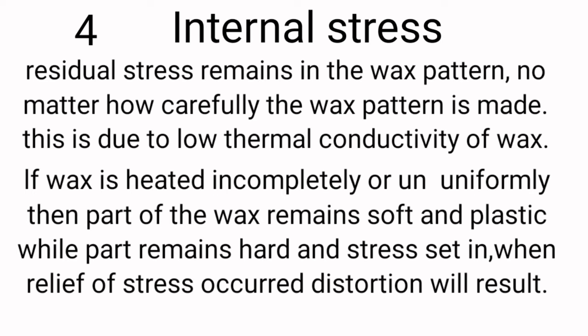Number 4. Internal stress. Residual stress remains in the wax pattern, no matter how carefully the wax pattern is made. This is due to low thermal conductivity of wax. If wax is heated incompletely or non-uniformly, then part of the wax remains soft and plastic, while part remains hard, and stress is set in. When relief of stress occurs, distortion will result.